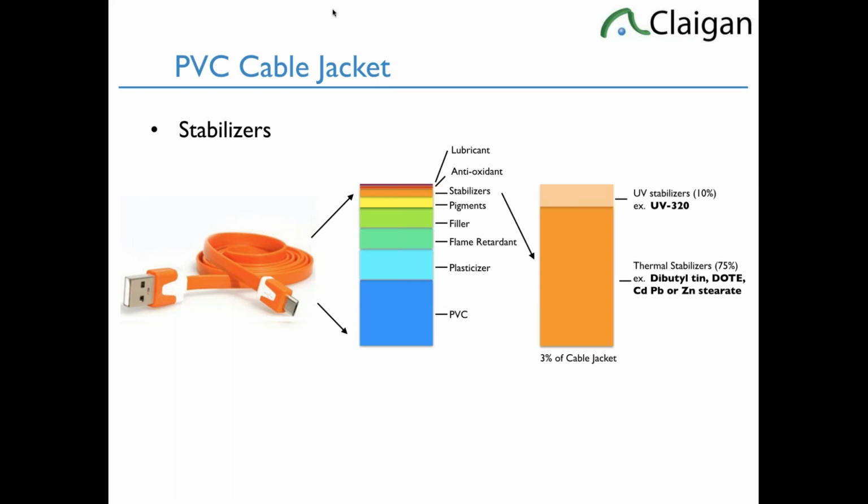Now, for the most part nowadays, there's zinc or calcium stearate stabilizers, basically zinc soap. But they can also be organotins. And we do see organotins, which are regulated under REACH as SVHC or REACH restrictions, depending on which one. Often enough, the most common at over 1,000 ppm is DOTE, the octyl tins. We definitely see the octyl tins. Infrequently, we do see them over 1,000 ppm. We very rarely see the dibutyl or monobutyl tins over 1,000. We see them all the time at 20 ppm or small numbers. We don't see them in high concentrations.